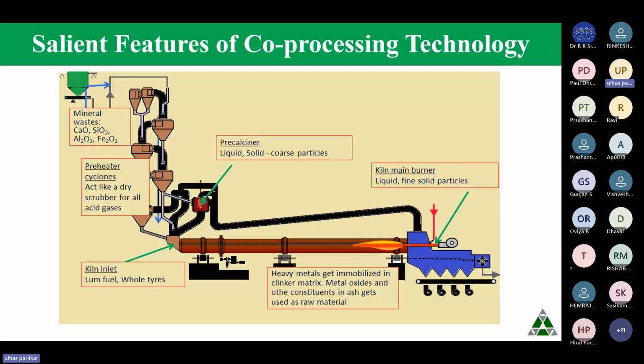What are the salient features of the cement kiln? If you look at a cement kiln, it is a gigantic facility. There is this brown cylinder that you see. This brown cylinder is called the cement kiln. And there's a flame here. This flame will have a temperature of more than 1800 degrees centigrade. We fire fuel through this particular burner here. This is a rotating kiln. It rotates at something like 3-4 RPM.